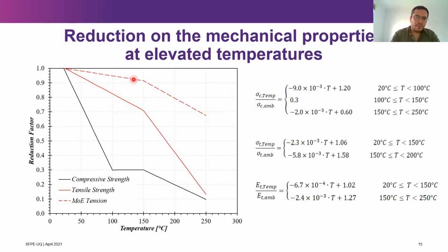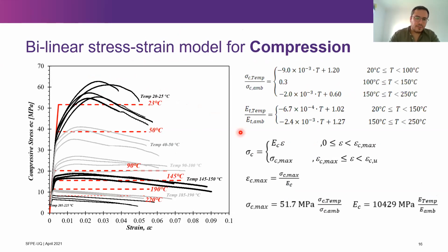So we describe that reduction with these equations, and based on that reduction, we propose stress strain models for compression and a stress strain model for tension. Tension is a little bit easier because bamboo is pretty much elastic in tension, and it has a brittle failure. Compression is a little bit more complicated because you see a lot of plasticity. And again, you can use very complicated models, but we ended up going for a simplistic approach and see if that simplistic approach could give us an accurate result, right? So we proposed to use a perfect elastoplastic model that obviously was changing as a function of temperature.